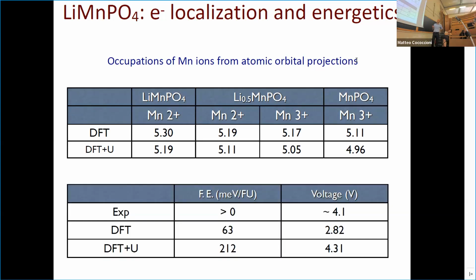But if you apply the same correction, you end up with a description that is not completely satisfactory, because the number of d electrons, compared to the ones that you get for the purely 2+ and 3+ states, is not very accurate, and also the energetics is not that great. In fact, you get much worse agreement with experiment for the average voltage of this material. So what is going on here is that the usual corrective function is not flexible enough for this type of